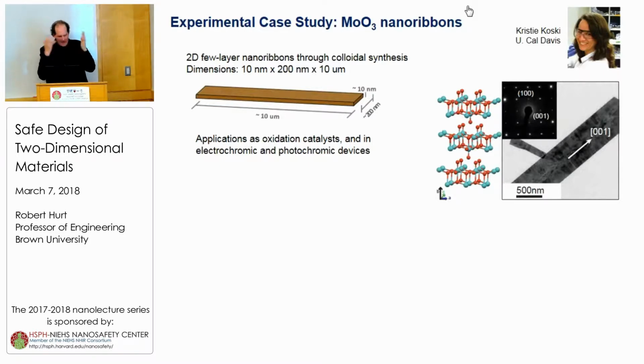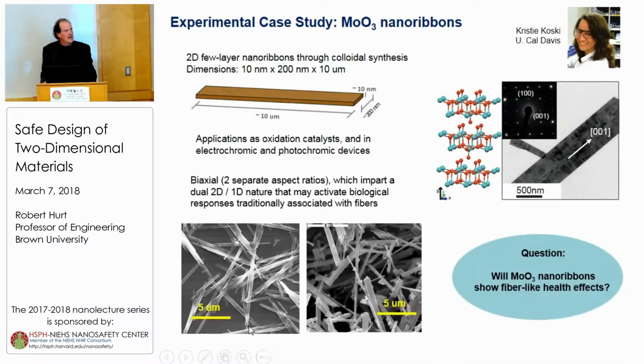It's Kristie Koski, a nanosynthesis expert, and she makes these 2D molybdenum trioxide nanoribbons in her lab. We lost her. She's now at UC Davis. And these nanoribbons are neat. They are truly 2D materials in that they have layered crystal structures, and you can exfoliate them down to monolayers. But they also tend to be long and thin. So I like to say they have a kind of dual 2D, 1D nature. If you just look at them casually, you might miss the 2D part, but you'll certainly see the one-dimensional nature they have. And they're remarkably similar in dimensions and size and stiffness to asbestos fibers.